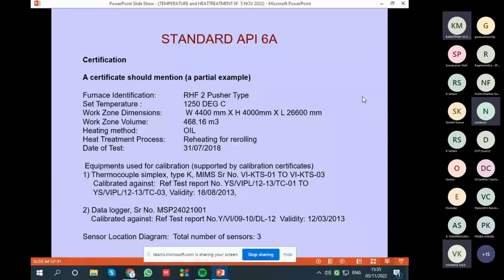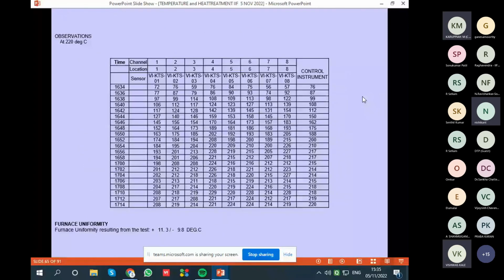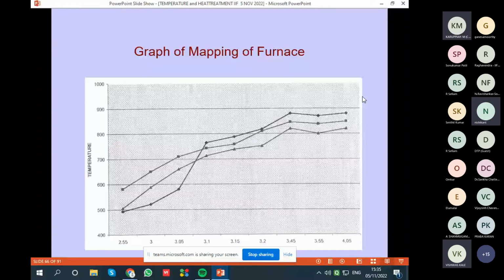These are my readings time wise. And this is the graph which I get from starting to beginning. If you see on the right hand side, the temperature has stabilized around 850 degrees. That data I am taking, and that variation I want to calculate. If the variation is more than plus minus 13, then there is something wrong in the furnace. The heaters may be incorrect, smoke location may be incorrect, etc., which I will have to correct.